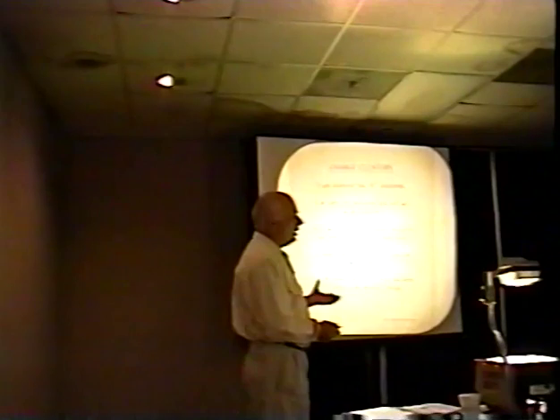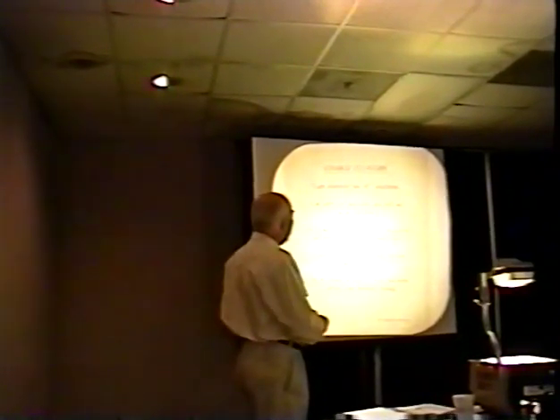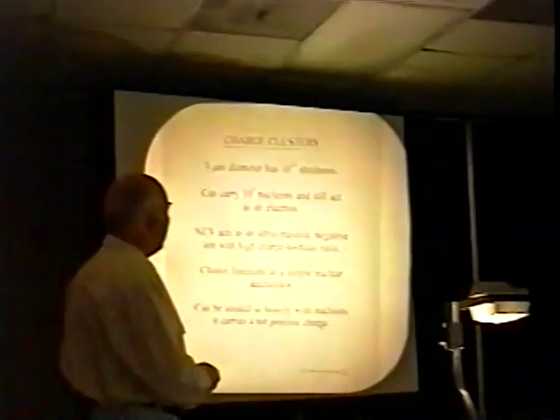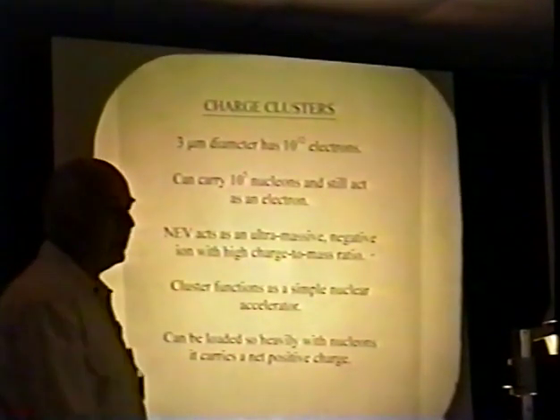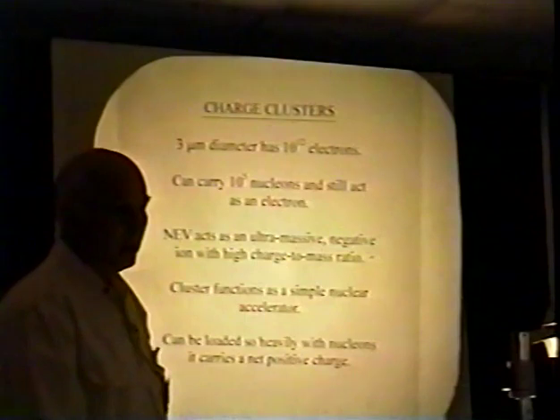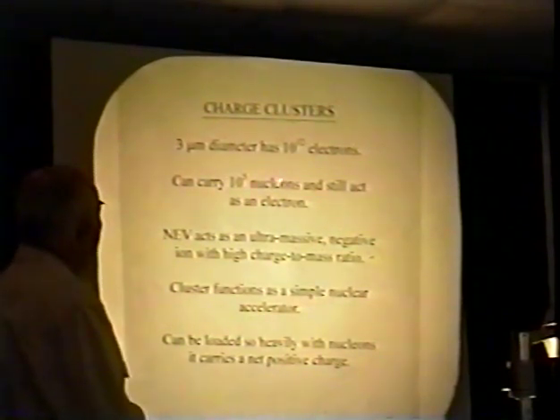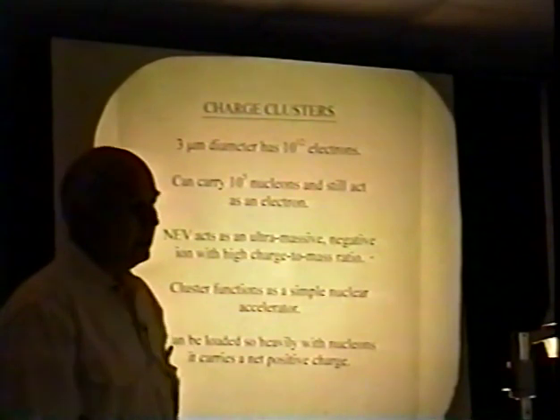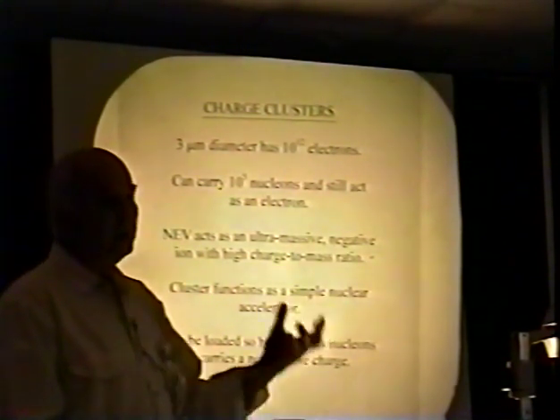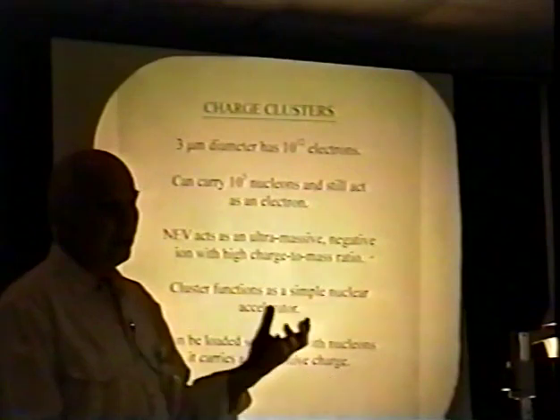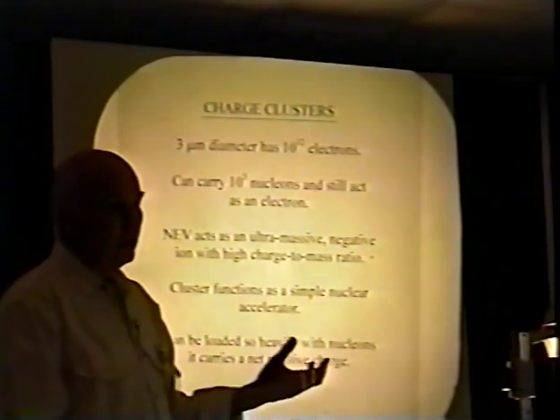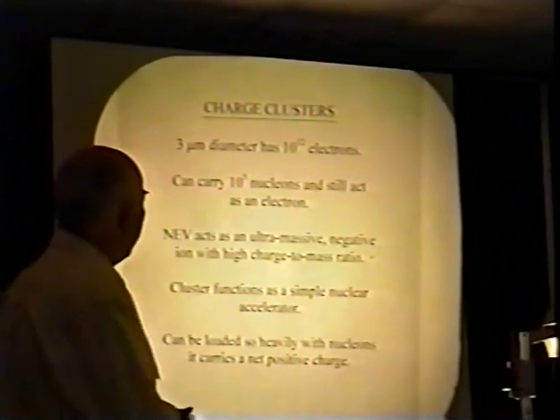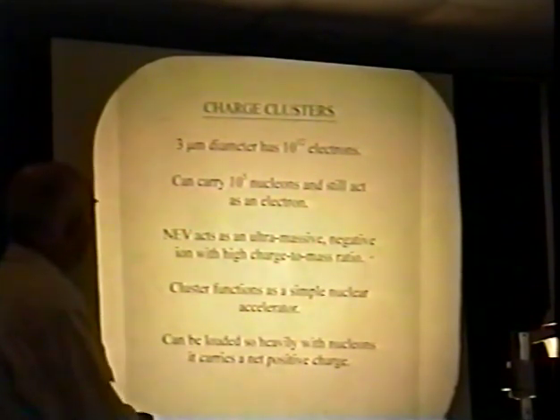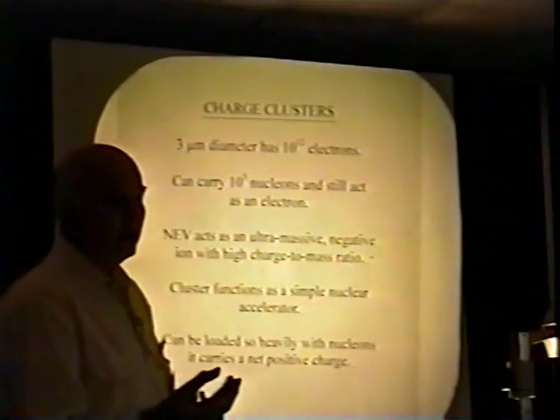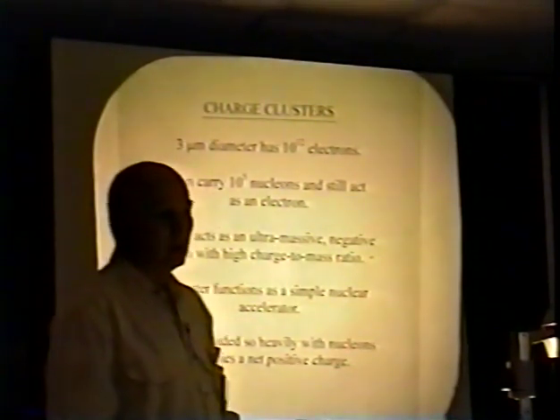The results have remained, very little has changed. I've been unable to move from the fact that, as I just described them, they're about 3 micrometers in diameter and contain about 10 to the 12th electrons. There are not any more than 1 million nucleons of any sort, any positive charged entities at least, within one of those clusters, by the best measurements I can make. This allows us to have 10 to the 5th nucleons still embedded in there and not be measured so far.